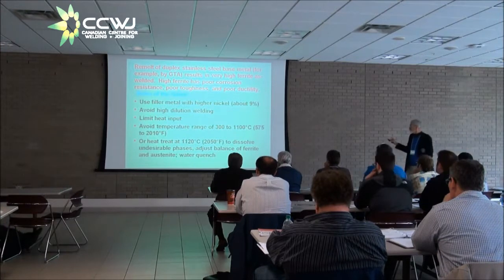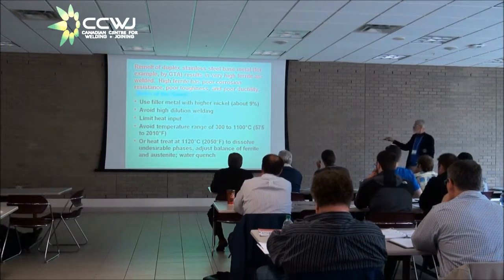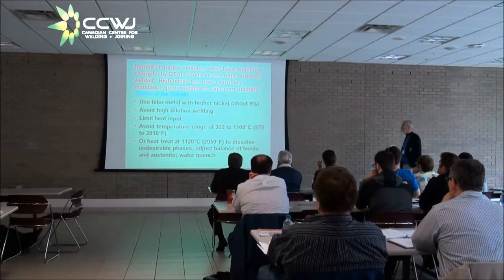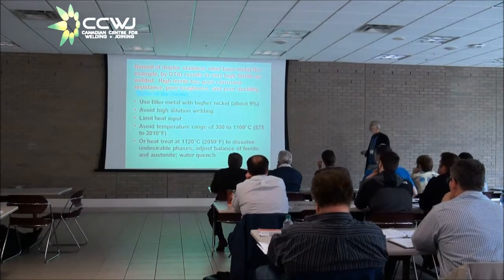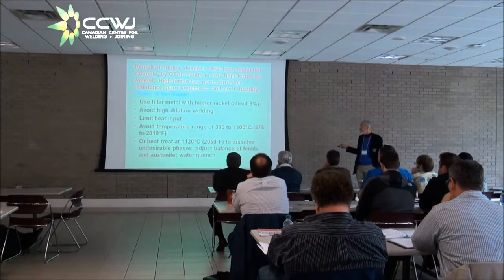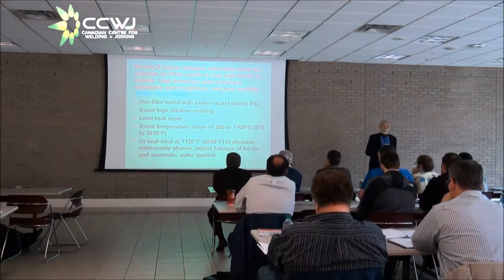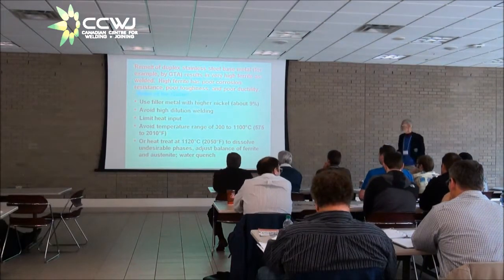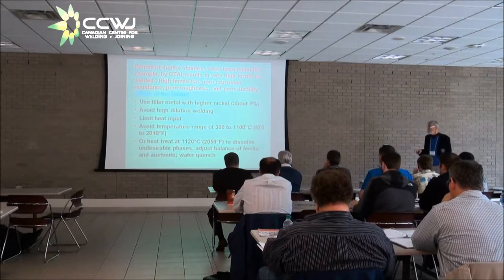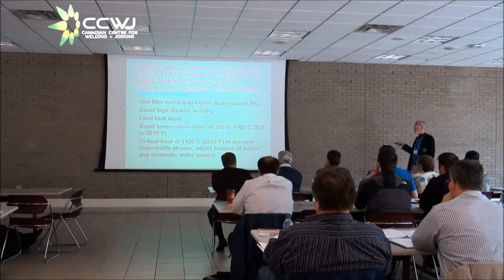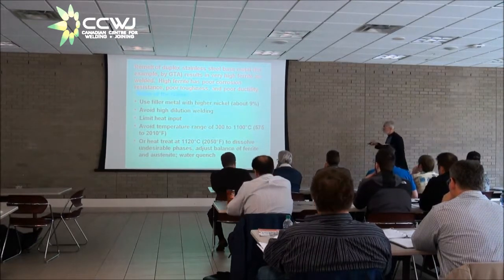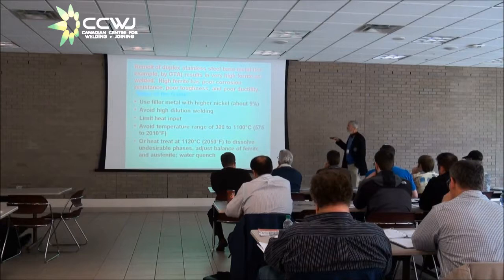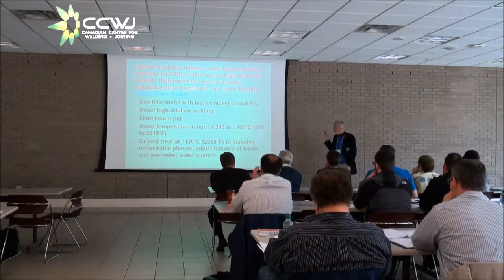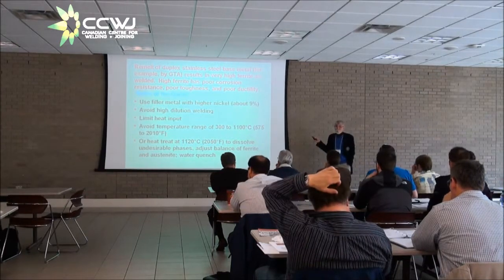You also have to avoid the entire temperature range from 300 to about 1100 degrees Celsius. Or you've got to heat treat at 1120 to be sure you're going to dissolve all the undesirable phases. And water quench. You've got to water quench more or less directly from 1120, or at least above 1040.